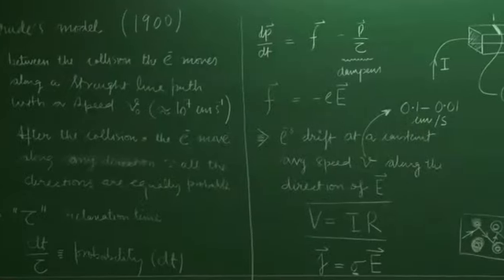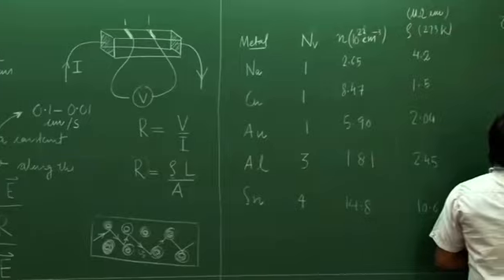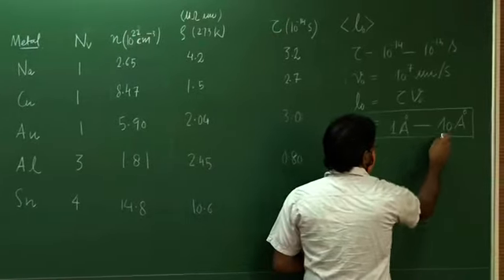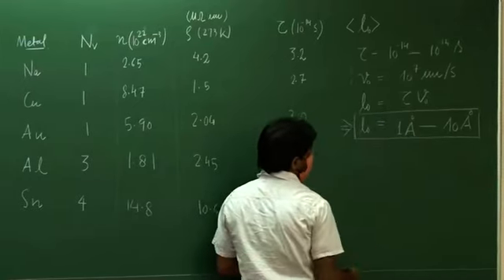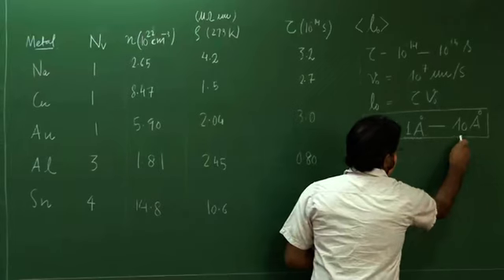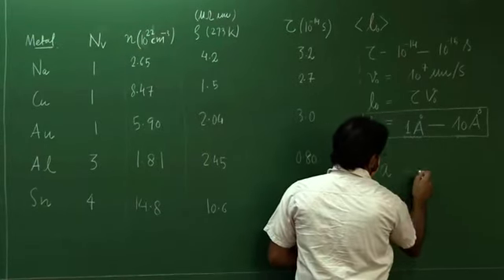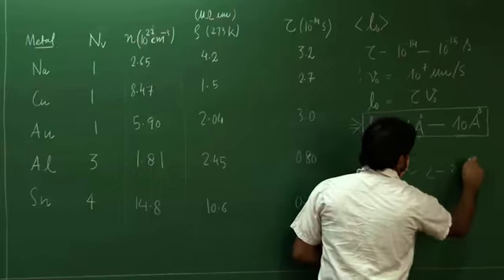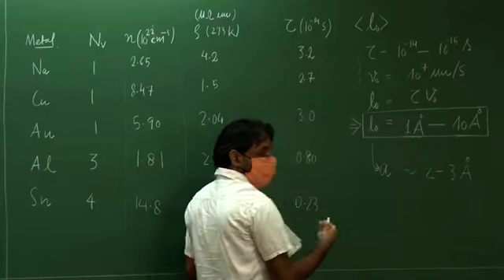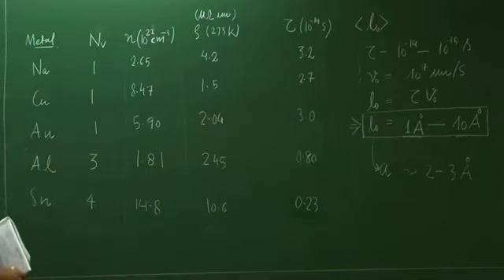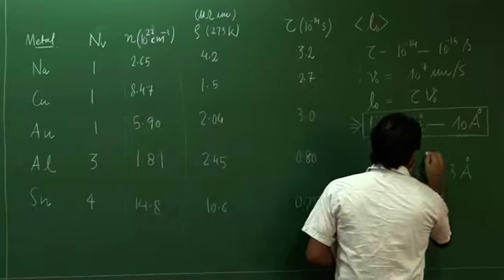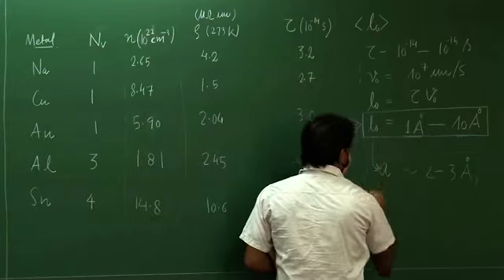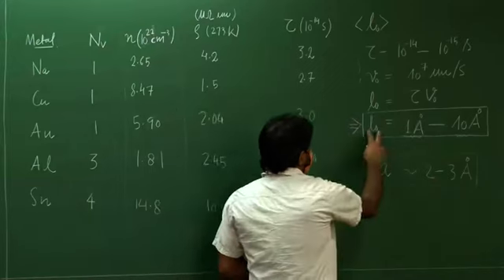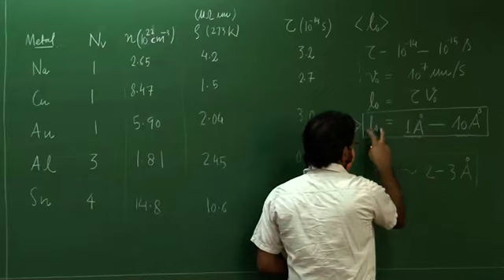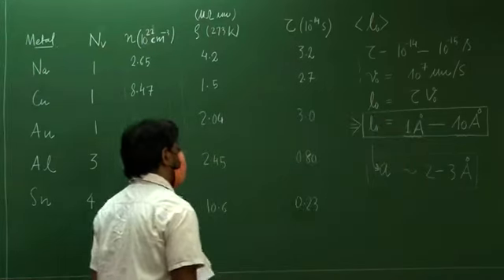On the other hand, to favor Drude, we see that the distance traveled by an electron between any two events is roughly comparable to the lattice constant. The lattice constant a is of the order of 2 to 3 angstroms. So l naught comes out to be not very different from the lattice constant, right? And that supported Drude's idea that, very roughly, the electrons are getting scattered by these ionic cores, because the distance that the electron travels between two successive scattering events is approximately comparable to the lattice constant of your material.